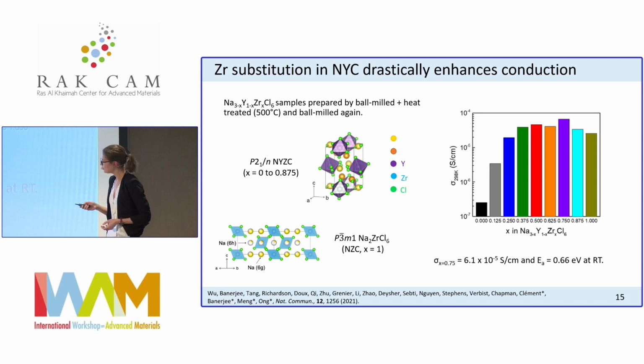And not unsurprisingly, as you start to induce sodium vacancies on the P21 over N lattice, or in this P bar 3M1 structure, you start to increase that conductivity with a maximum at 75% zirconium substitution, which leads to a conductivity on the order of 6×10⁻⁵ Siemens per centimeter, which is okay, but still not great conductivity.